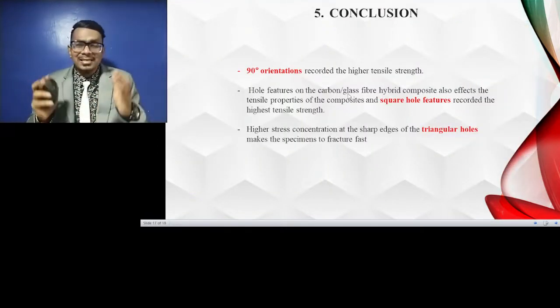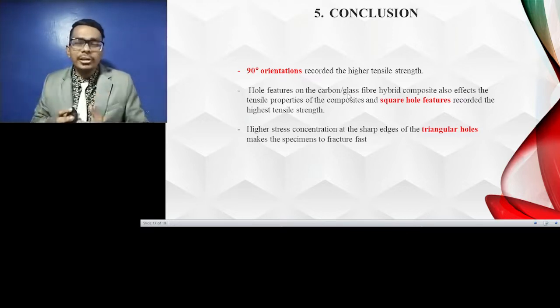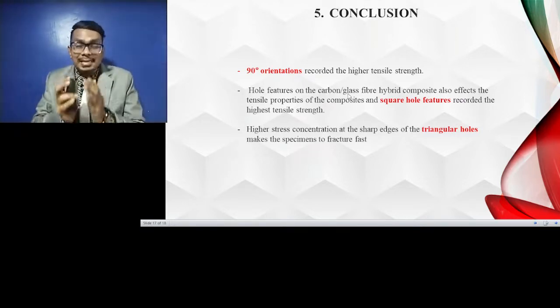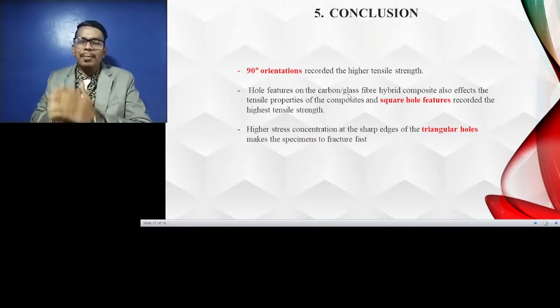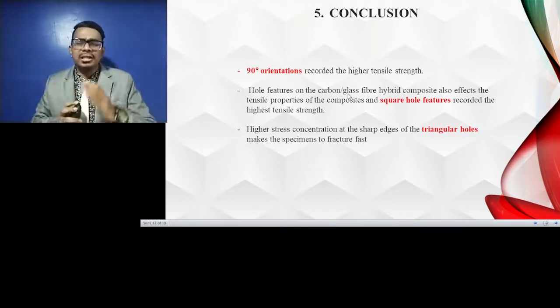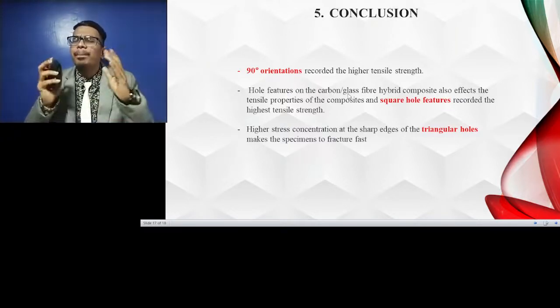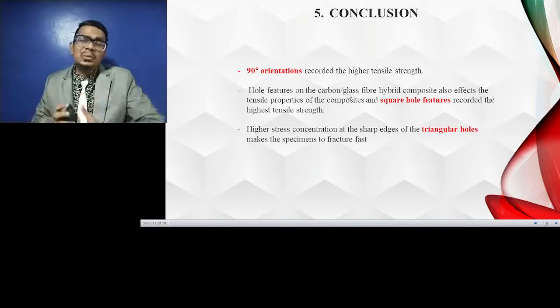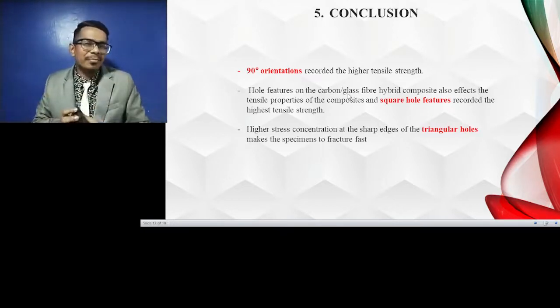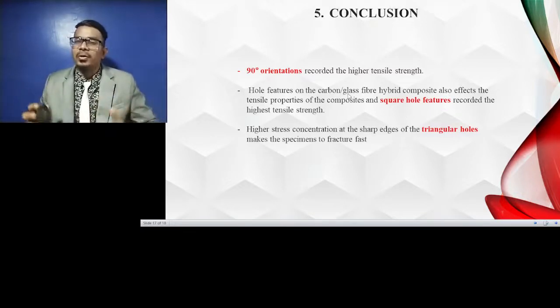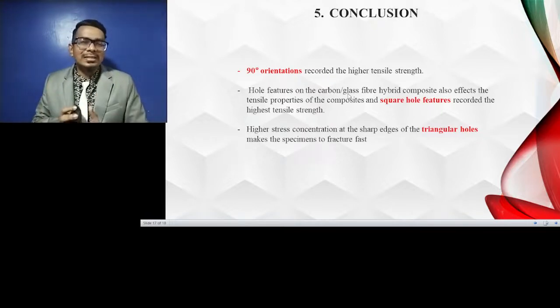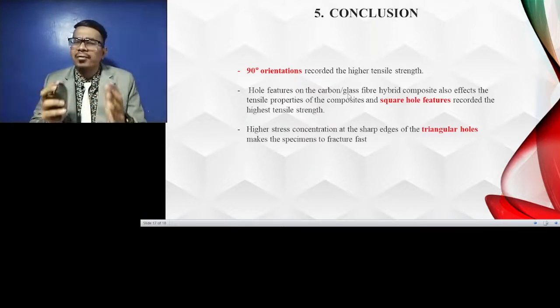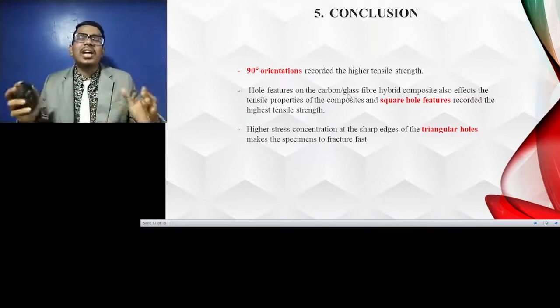Last but not least, as a conclusion of my research, various orientations and hole features affect the tensile properties of the carbon glass fiber hybrid composite. As the best orientation, 90 degree was chosen because the tensile force applies perpendicular to the direction of the fiber arrangement. In addition, as the best hole feature, the square hole was chosen since it recorded the higher tensile strength because of its less sharp edges. Finally, based on visual observation of the fractured surface, it was concluded that holes with sharp edges crack first and the cracks happen at the sharp edges of the hole.